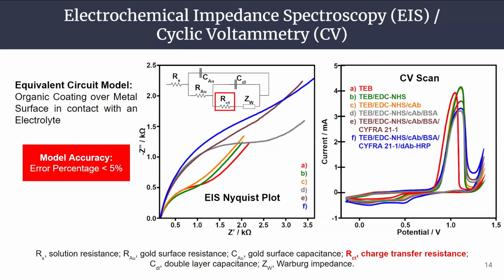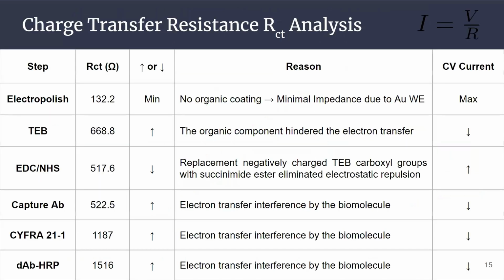To understand the process, we first characterized the sensor. Electrochemical impedance spectroscopy, or EIS, gives us sensitive information about surface modifications, and we designed an equivalent circuit model with an accuracy of more than 95% to describe the charge transfer resistance of the sensor, which was further compared to cyclic voltammetry, or CV scan.